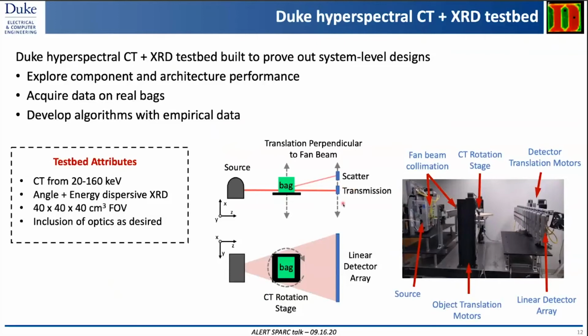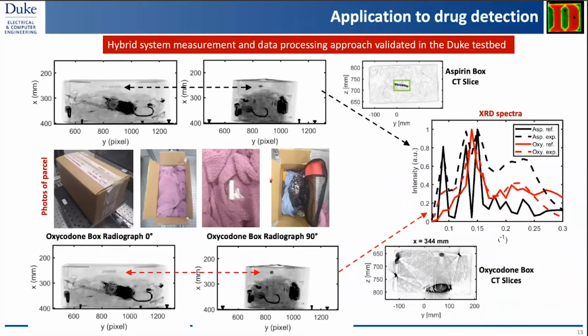So this system that we have at Duke allows us to do full CT, helical CT, or slice-by-slice CT with multi-energy detectors. So we have an X-ray source, translation and rotation stages for the bag, and an array of energy-dependent or energy-sensitive X-ray detectors on a translation stage that can scan through. So we can measure the transmitted signal at a range of different object orientations, as well as a full angle and energy dispersive X-ray diffraction signal. And we have space in here to put whatever X-ray optics for modulating the beam or shaping the scatter as we see fit.